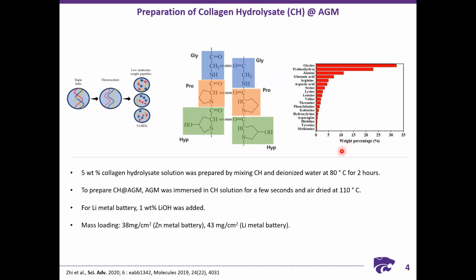This is the weight percent of collagen constituents present in pig skin. You can see that glycine, proline, and hydroxyproline are the major constituents. So what they did is they took 5% of this collagen hydrolysate, mixed it with deionized water and stirred it at 80 degrees centigrade for 2 hours. This prepares a 5 weight % collagen hydrolysate solution.